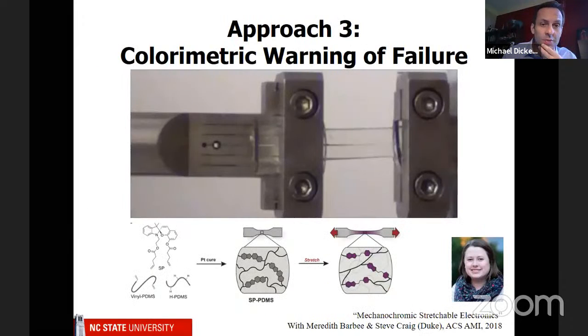And this is the third and final approach, which is to actually use the silicone. So this is a piece of silicone. And remember, silicones, if you pull hard enough, you can break them. So what we did, in collaboration with a really good student named Meredith Barbee, was integrate a molecule called a spiropyran. That molecule is integrated directly into the silicone network, into the PDMS silicone.